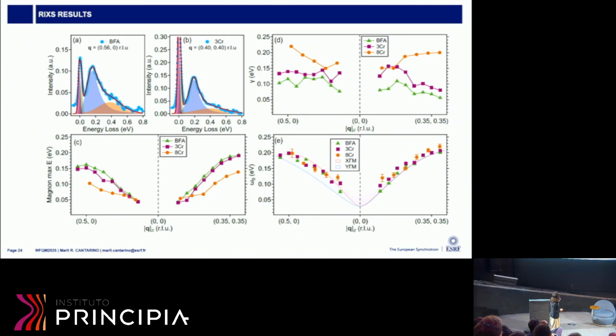As I mentioned, when you look at the propagation frequency, the maximum of the peak is very similar between the parent compound and the 3.5% chromium sample. But when you have the 8.5%, you start to have this damping.